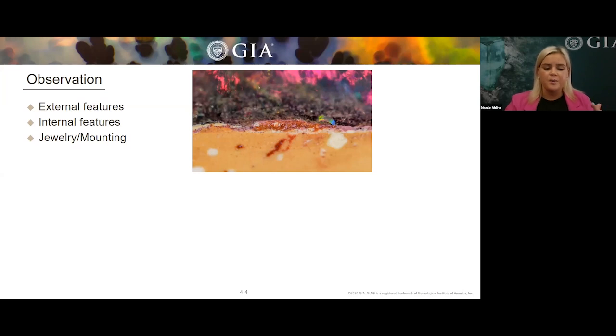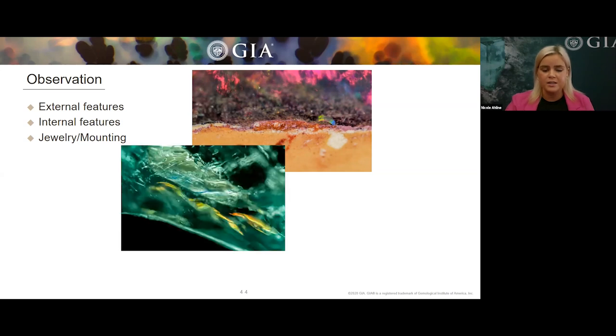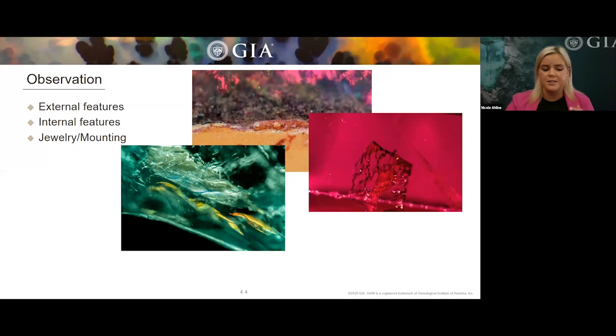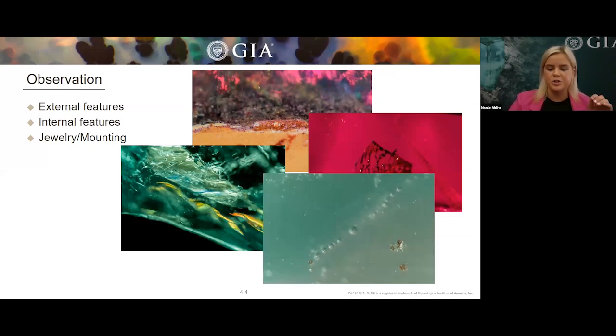Internal features, we're going to be looking for and documenting areas of the stone if it has been dyed or clarity enhanced. So this is a classic flash effect from a filled emerald fissure. We're going to be looking for evidence of natural versus laboratory grown. So what we see here is a flux fingerprint in a laboratory grown spinel. And here, this is a stringer of gas bubbles found in a glass bangle imitating jadeite.